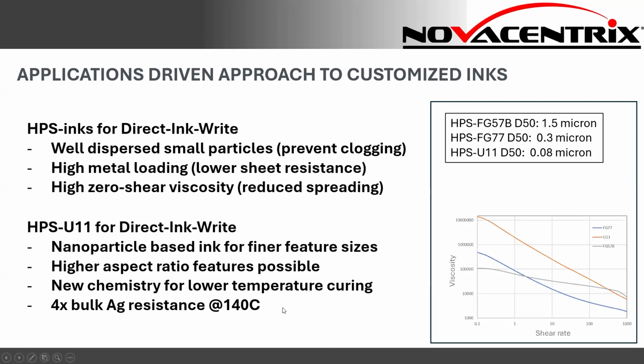So if you want to print a 100 micron line, you do not want it to spread out to 120 microns, right? This week we were talking to a customer who uses the V1 with one of our copper-based inks, and he was very happy that he could actually get close to 60 micron lines. So that's one of those things that we need to be aware of. So here's a quick overview of how we do that with the U11 inks. The U11 inks are nanoparticle-based inks, but not only that, the nanoparticles are a lot smaller than FG77, right? The other part is what I was saying earlier.